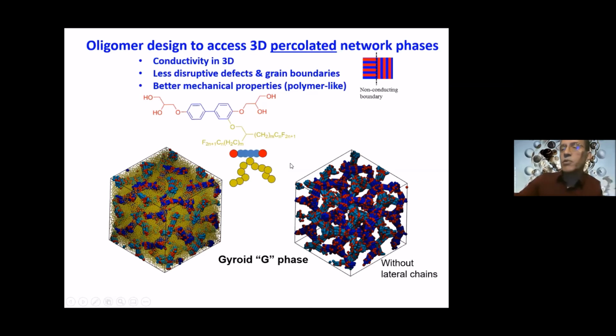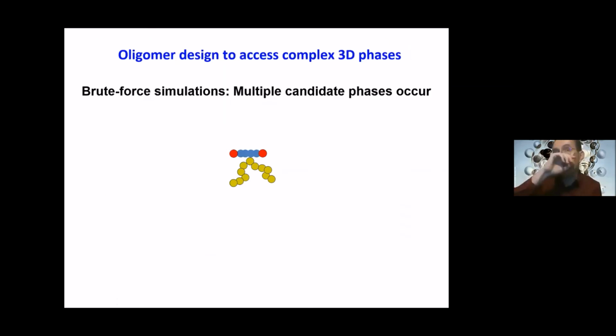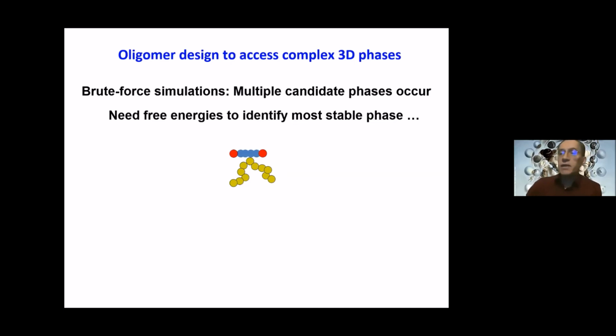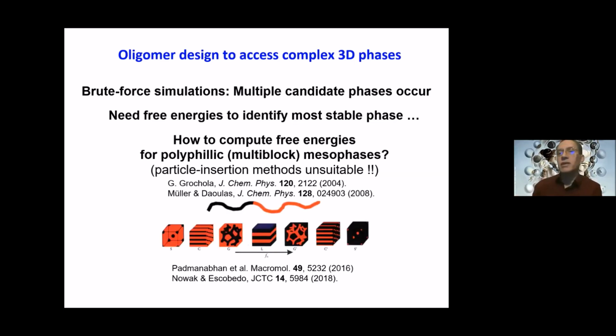But beyond that, we wanted to understand why this molecule forms this interesting phase, right? And for example, understand to what extent it's all about energetics, or perhaps entropy also plays a role. So to answer this question, you can just put these different molecules in a simulation box and see how they assemble. But if you do it, you will find that oftentimes you get different phases that form spontaneously, right? So there are multiple candidate phases, and so it would be hard to tell which one is more stable thermodynamically, unless you're able to measure free energies. But how do you do that for phases of this sort, that are really examples of phases that are formed by amphiphilic molecules or diblock copolymers, as shown here? And amongst these mesophases, the G phase I told you about will be one of them.